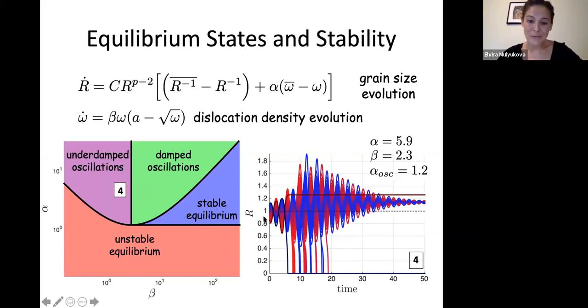Another case: if you start off with some sort of heterogeneous distribution of grain sizes that are unstable, and the kinetics of dislocations and the kinetics of grain boundary motion are such that the rate at which the dislocations can adjust to the changing grain size is relatively slow, you may have overshoots and undershoots as the system moves towards a steady state. So what this means is that in the transient stage of your material deformation, the material may weaken and harden, and your dislocation density and grain size may increase and decrease through time at some characteristic time scale.